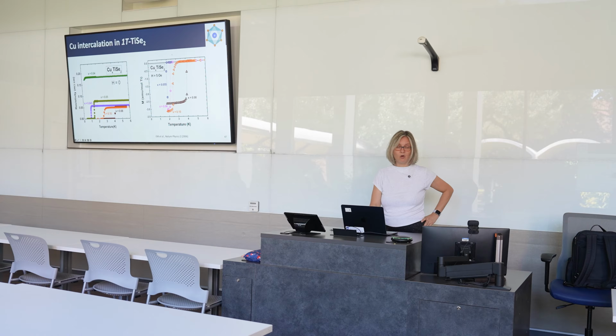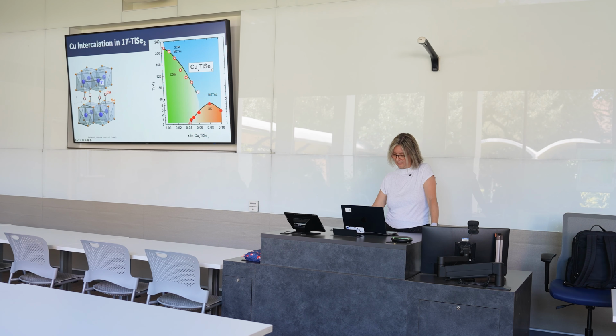The susceptibility also shows the signature of the superconducting transition with a drop at the TC. What you should notice is that the superconducting transition, which occurs at about 4% copper in the green curve over here, moves up in composition until about 8%, and then at 10%, it changes its mind and goes back. And that's reflected in this phase diagram.